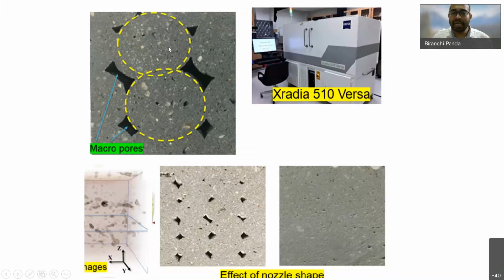But now imagine the material you are printing is a slightly slumpy material. What is going to happen? This cylinder is going to turn into an ellipse, and as a result you are going to get less pore in the structure. So the key point here is that in concrete printing, it is not only about the material, but also the process parameters that affect the final print quality of the structure. If I am using a very stiff material and my nozzle is circular, the layers will be exactly the shape of my nozzle, and we are going to get more porosity. But the same nozzle can be used with a very slumpy material which is going to deform after printing, so ultimately it is going to minimize the pores. And instead, if I simply print the whole structure with a square or rectangular nozzle with a higher overlapping, this porosity can be further minimized.